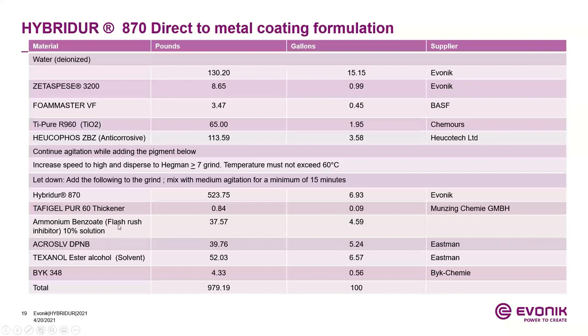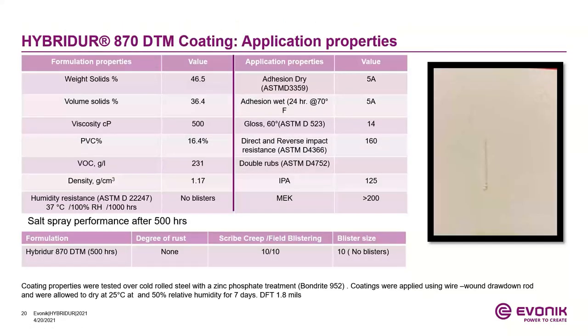You blend the ammonium benzoate, which is a flash rust inhibitor, the coalescing solvents, which are DPnB and Texanol ester alcohol, with a surfactant here. So the pigment dispersion is let down into a mixture of Hybridur and this for component share, which is basically benzoate, DPnB, ester alcohol, and later you add a polyurethane thickener to get the viscosity and rheology properties for the coating. And we tested this in several applications.